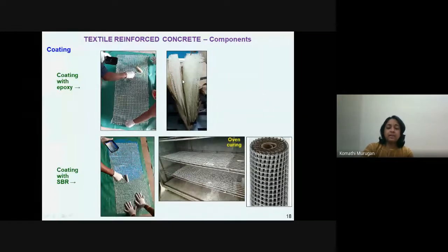What is generally obtained when we coat a textile with epoxy are stiff textiles. These stiff textiles are stiff in the sense that they are not flexible. They cannot be rolled, as shown in this picture here. They are planar, and they can be used in casting plain elements such as facade panels or slab panels. What is shown here below is the coating of the textiles with SBR, that is, styrene butadiene rubber. The procedures are quite different. For example, if we coat the textiles with epoxy, we have to leave the textile undisturbed for about 24 hours, take them after 24 hours and start using it.